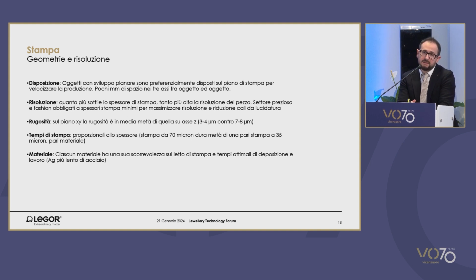It is interesting to focus on the layout of the items, opting for the plane of the biggest encumbrance of the item to guarantee support in terms of gravity. Items have to be placed a few millimeters one away from the other, so you can actually fill the surface quite well. Trivial as it may sound, the higher the resolution, the better for the jewelry world. With our powders, the roughness you obtain at the end of the printing process is approximately 4 microns on the XY planes. It is higher on the Z-axis, about twice as much. And this depends, of course, on the binder elimination phase.